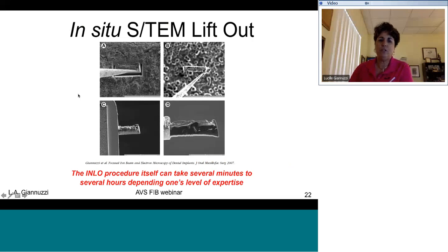So there's a bunch of different ways to do this. One of the ways is to totally FIB mill a sample free, then you insert a probe that's mounted either inside or on the chamber of your microscope. To get it to attach to the sample, you need to use platinum deposition or carbon deposition or tungsten deposition or whatever deposition you have. People call this welding. I don't like to call it welding because you're not welding. You're essentially just attaching the needle to the sample using your ion-assisted CVD process.